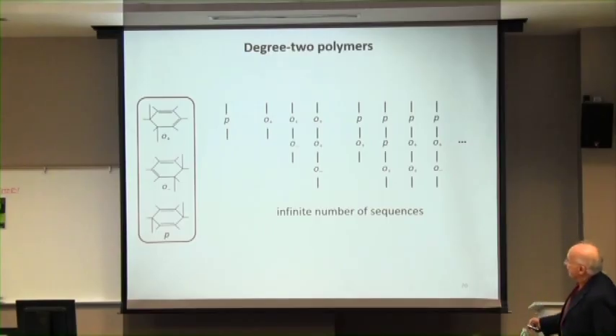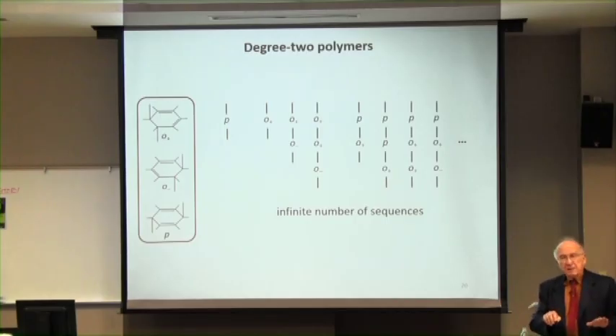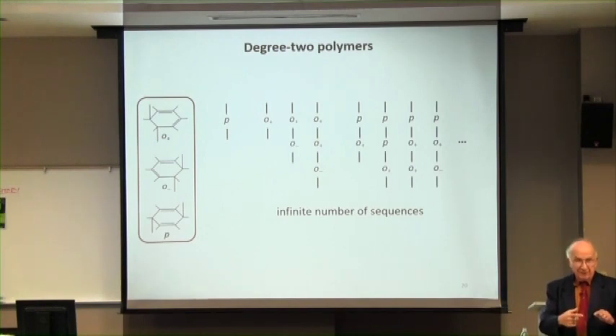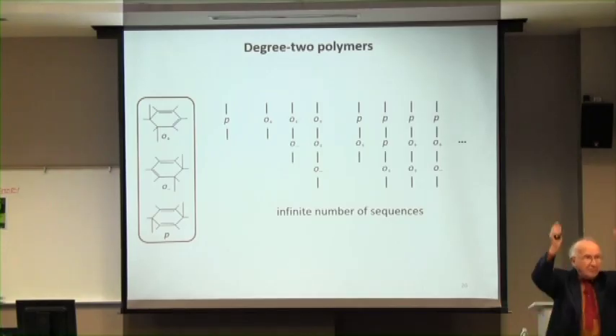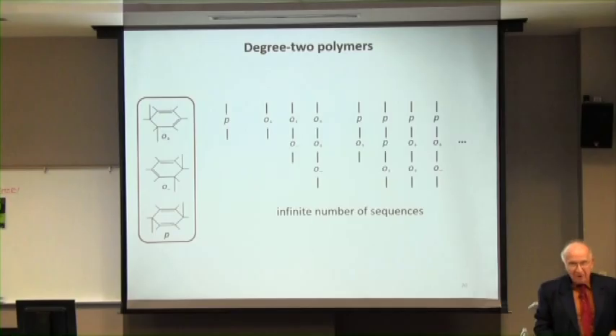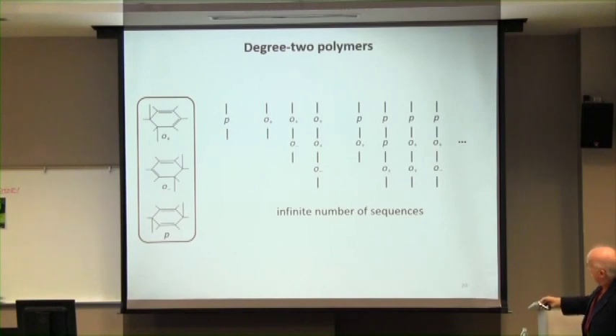For instance, here are the building blocks of the degree 2 polymers. So degree 2 means everything that was a benzene ring retains 2 double bonds. Just 2 are saturated. So the 2 that are saturated can go off, 1 to the next unit, 1 down. So here is what they will not do. They will not both go up, because that's the end of the world. The polymer doesn't go on if they both go up. We want an infinite polymer. So 1 has to go up, 1 down. But you recognize this as you look at it, that this is chiral.